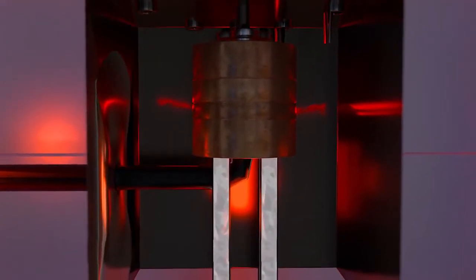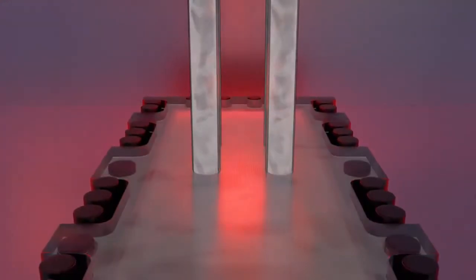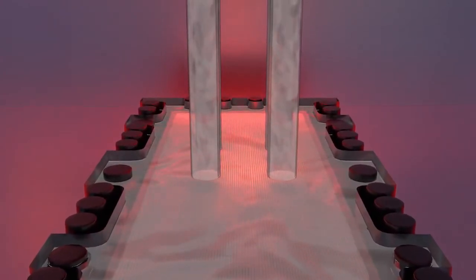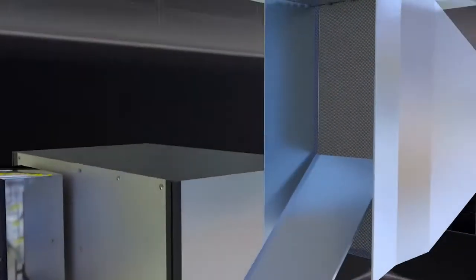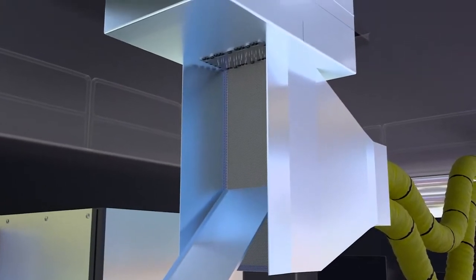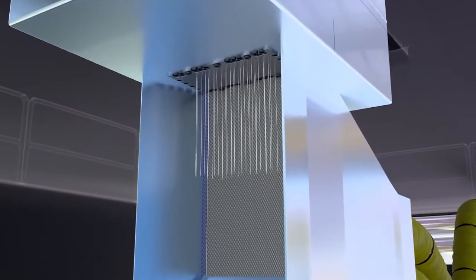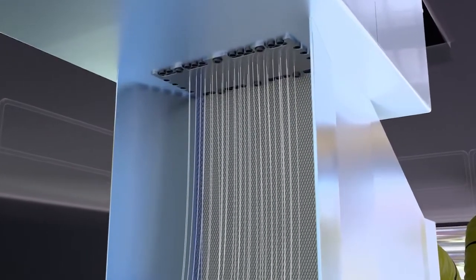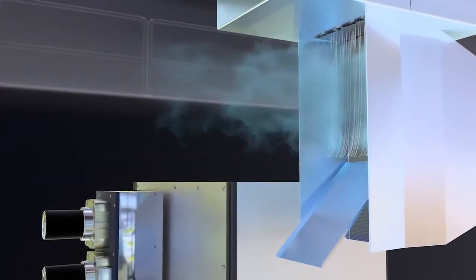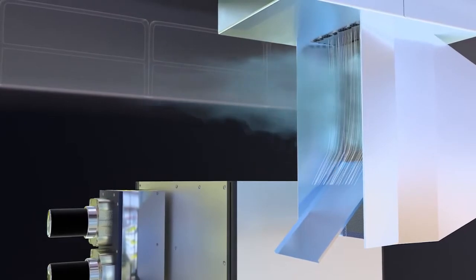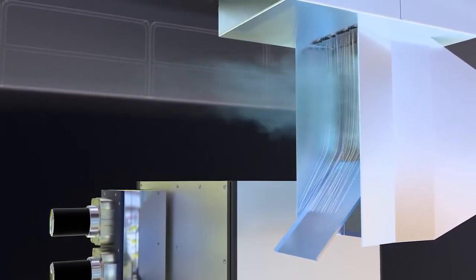The melted polyethylene moves through a filtration system to remove solid particles such as dirt or sand. The melted plastic is then pushed through a spinneret, a plate with hundreds of passageways determining the number of filaments per strand. The melted pellets form thin filaments and cold air then rapidly cools the filaments to achieve solidification.